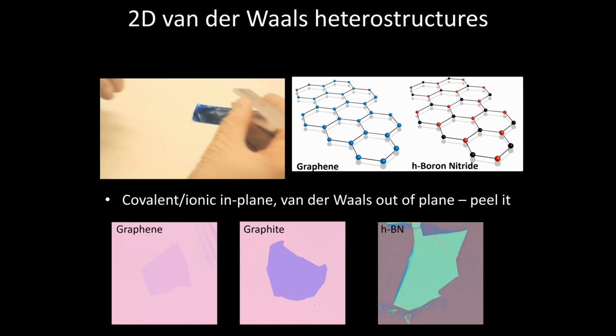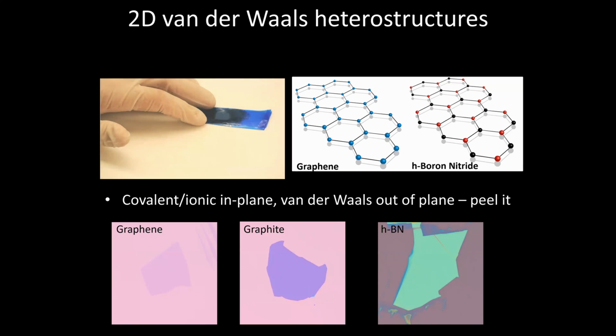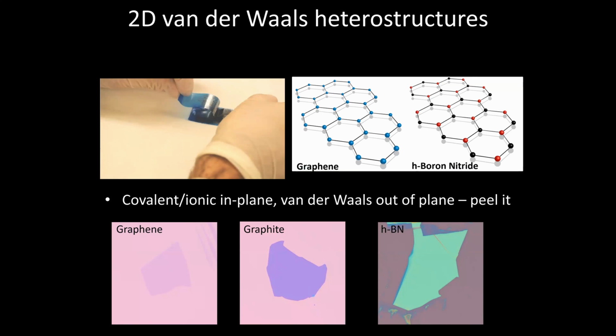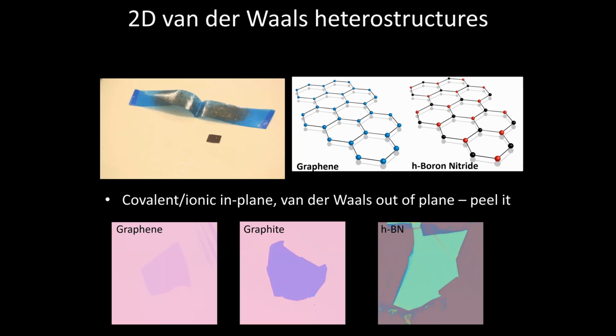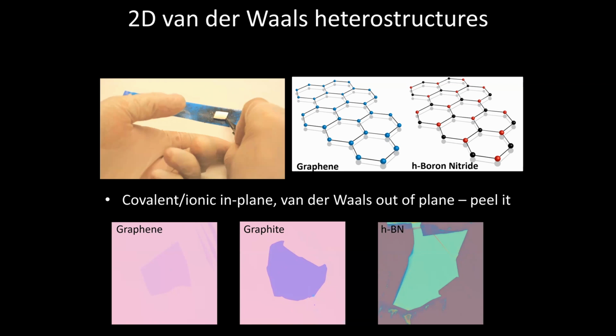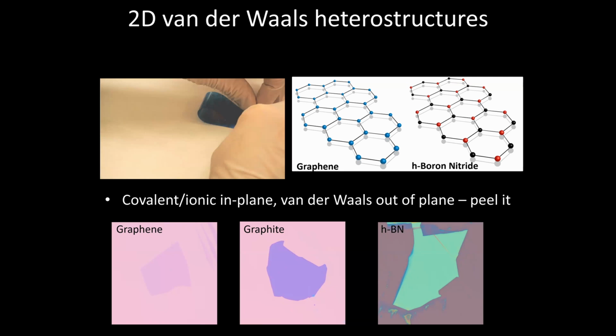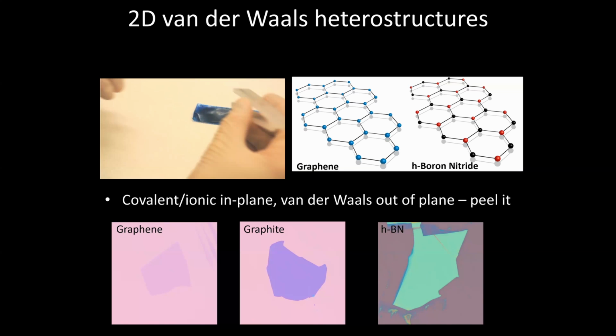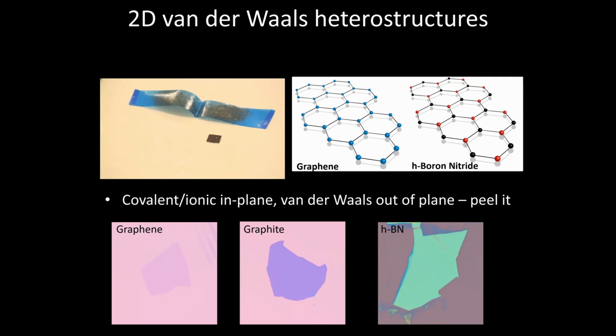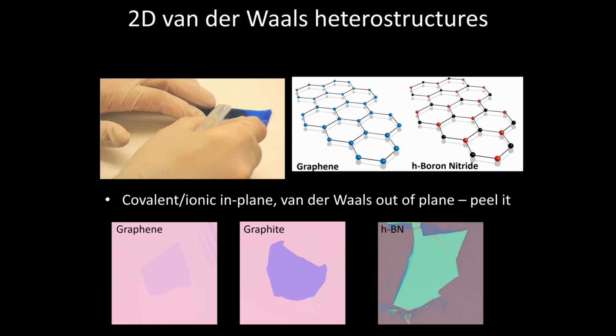It has exactly the same crystal structure as graphene, but rather than having two carbon atoms on the vertices of these hexagons, you have a boron and a nitrogen atom on every other vertex. So this is an ionic crystal, and it has a very large band gap in the deep UV, whereas graphene is a semi-metal. So you can use this as a substrate and as something that you use essentially to scaffold these heterostructures, separate layers, or use it as a dielectric so that you can apply gate voltages.